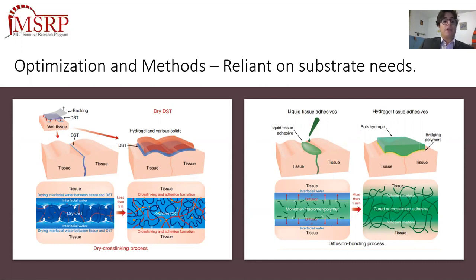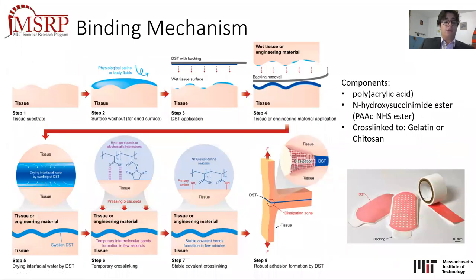For example, spider web glues, which remove interfacial water from the contact surfaces in order to form bonds. Therefore, adopting a cross-linking mechanism to remove interfacial water and form adhesion on wet tissue surfaces was designed. Some components found in this polymer are polyacrylic acid and PAAc-NHS ester, which are cross-linked to gelatin or chitosan. Negatively charged carboxylic acids in the PAAc-NHS ester facilitate quick hydration and swelling of the DST.